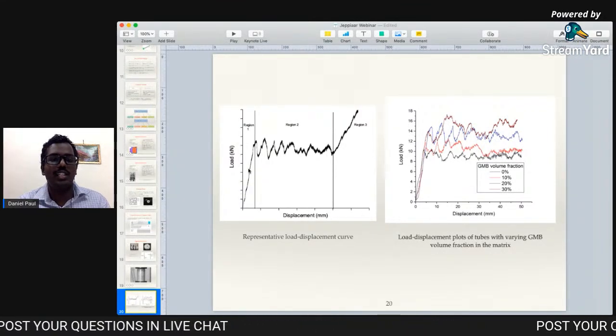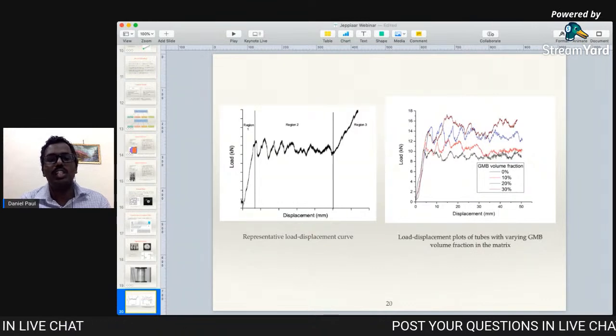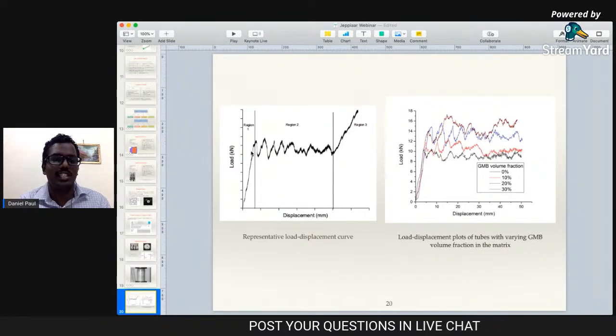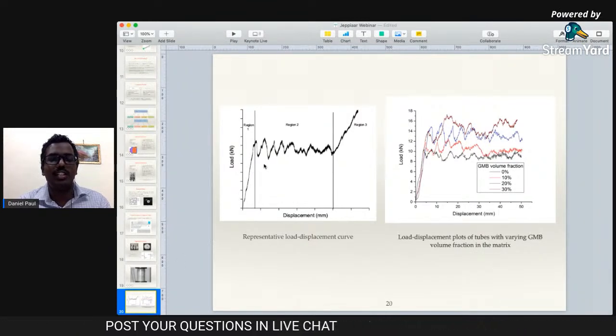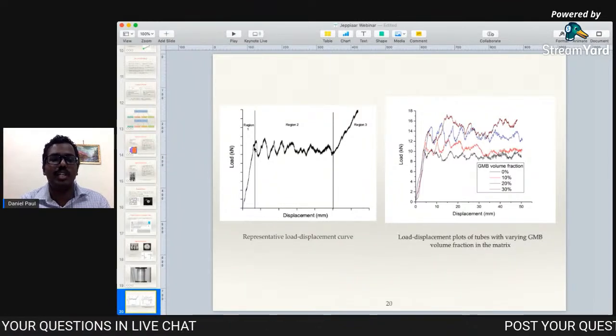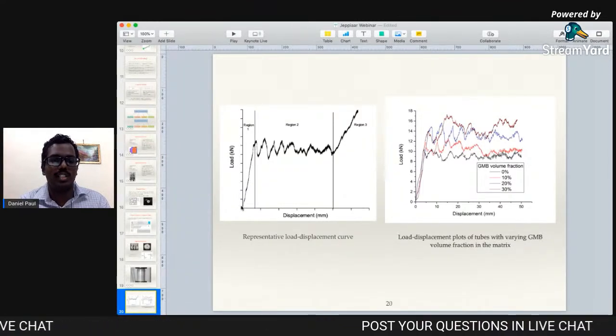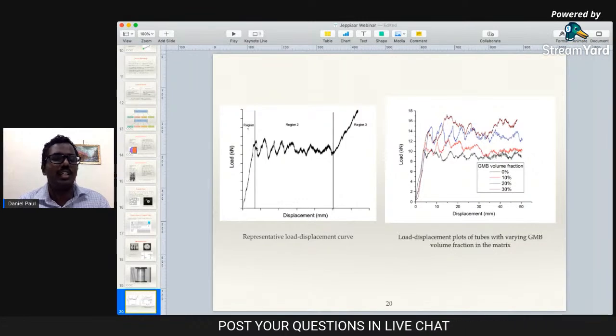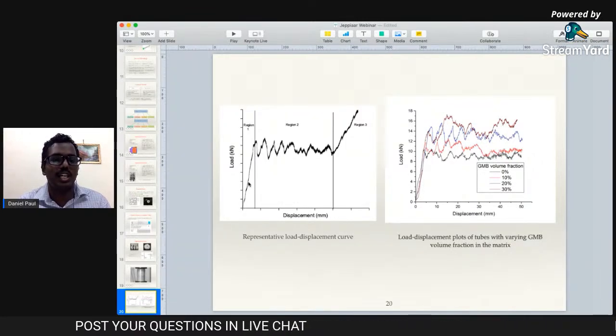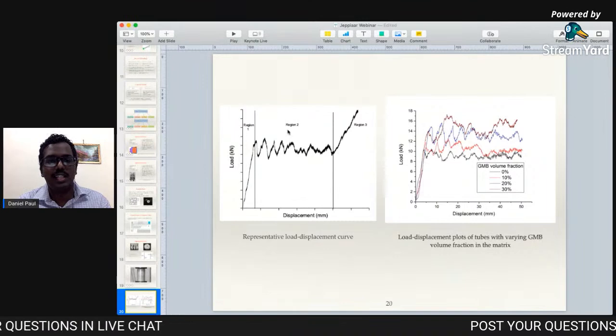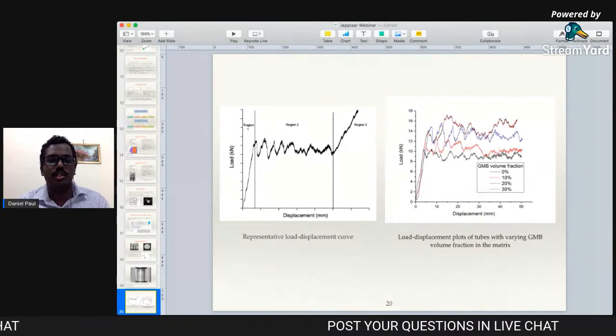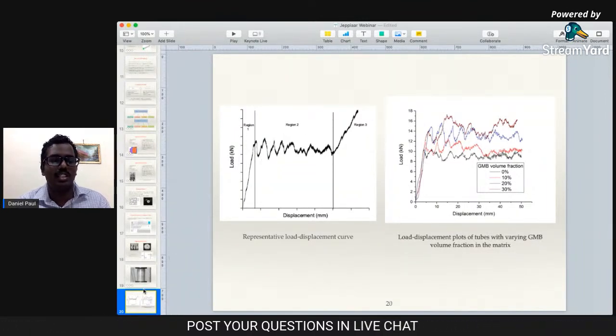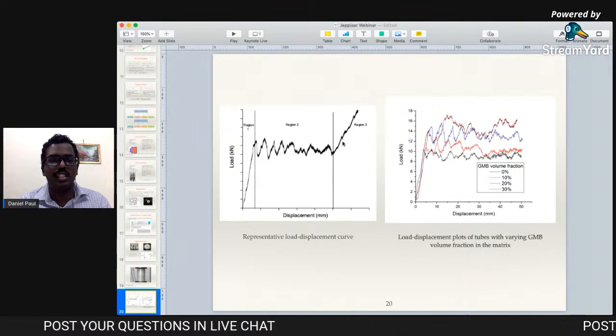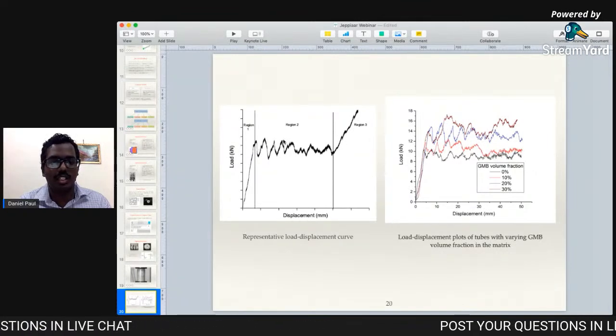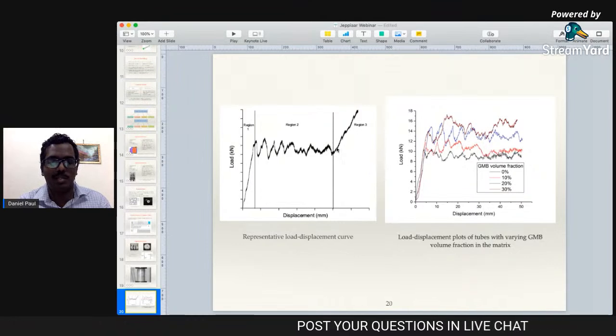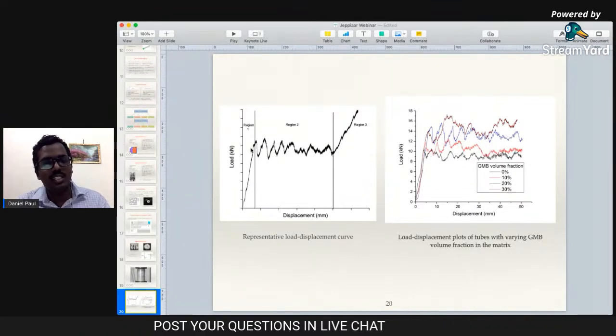And we can see that there are three regions in this one. The initial first region is where the chamfered part of the tube is compressed. It's almost like a linear elastic material, like any other material would start to deform. But the second region is what is important in these progressive failure based structures. In the second region, we can see that there is a lot of undulation and up and down movement in the load displacement graph, and it extends for a long time.